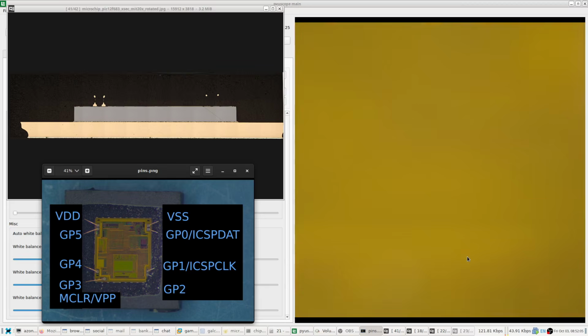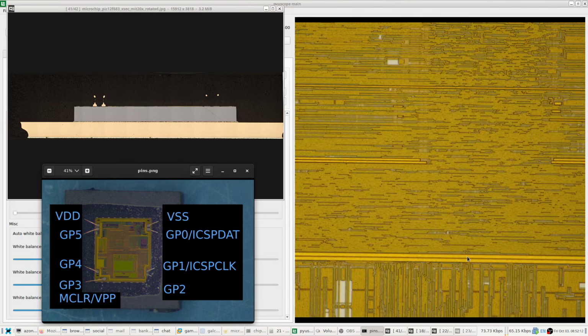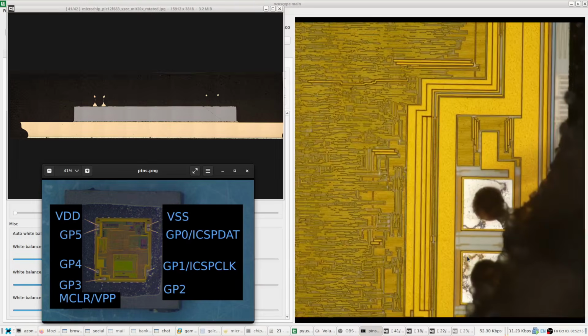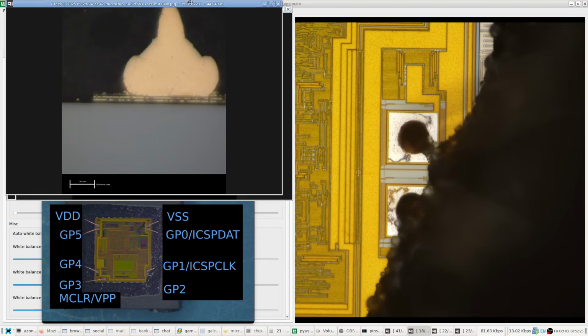And then as we switch to a higher magnification view, this is with the 20x objective. We're going to go down to the bottom right corner and take a closer look at the GP1 bond pad. And seen here in cross-section, this is this bond on the other test sample. And so we can see that there's this little wire here, which is probably this one here that we're looking at end on. And then we've got 1, 2, 3 metal layers with some vias visible between them on the perimeter of the bond pad. And then on either side here, we can see a little bit of squeeze out. That's pretty typical. If you etch off a ball bond, you'll see a noticeable crater in the pad where the bond had been.